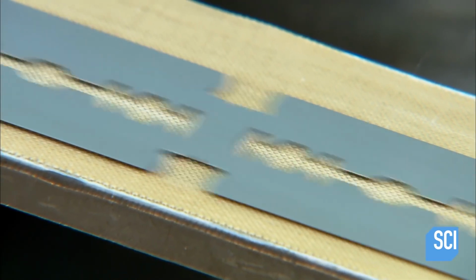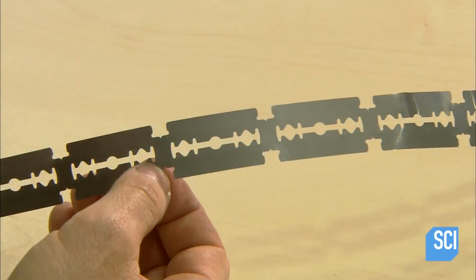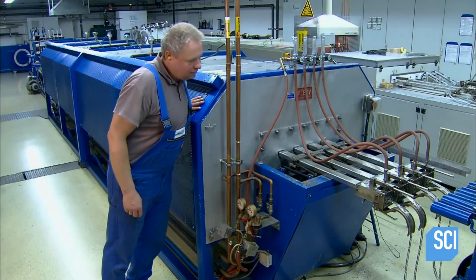At this stage of the process, the stainless steel is very soft, as pliable as paper, so they now harden and strengthen it through a 4-step heat treatment process. Step 1. They heat the blanks in a furnace to just over 2000 degrees Fahrenheit for about 30 seconds. Step 2. They briefly submerge them in cold water. This is called quenching. Step 3.